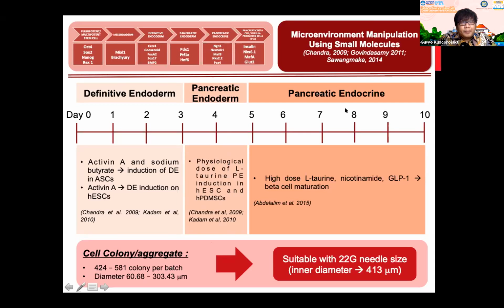Finally, the last stage is the maturation stage. In this stage, we use a high dose of L-taurine, also nicotinamide, and GLP-1. We use three molecules in this stage. The result of this study is consistent with a previous study performed by Abdel Alim, who conducted this research in 2015. And how about the cell aggregate with the size of the needle that we choose?